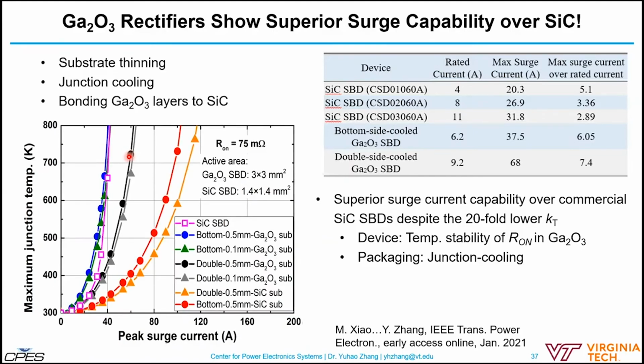However, if we bond the gallium oxide layers to a silicon carbide substrate, we are essentially leveraging both the high thermal stability of the gallium oxide junction and drift region, and the high thermal conductivity of the silicon carbide substrate.